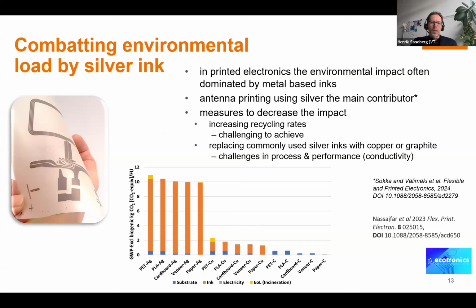because that is also in fairly large amounts compared to many of the active materials or separate components in a flexible electronics device. So if you do the LCA of a printed electronics device, you will see that the printed silver is a main contributor to the poor results. In this case, we have looked into the CO2 equivalent of different solutions for the same device, and there you see that changing substrates between PET and bio substrates doesn't change too much.